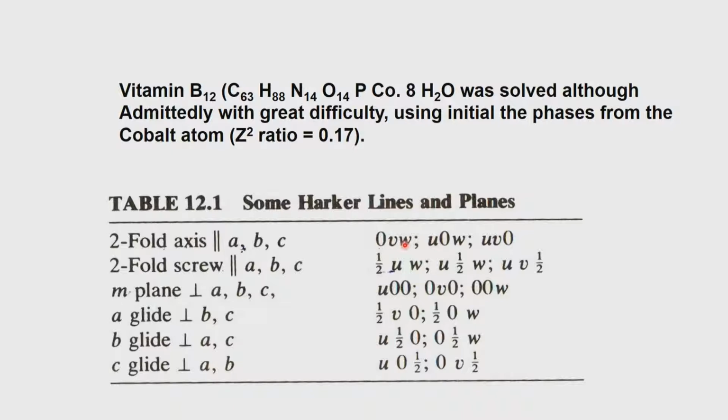So, the projection plots will carry the symmetry information. If there is a two-fold symmetry, the two-fold symmetry information, even though lost in the main Patterson, will be present at the two-fold screw position corresponding to parallel to A, parallel to C. We have these positions. So, if we now look at the section at half, you will get solutions for U and W.